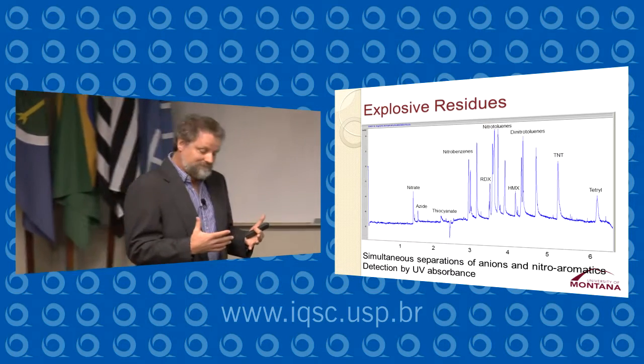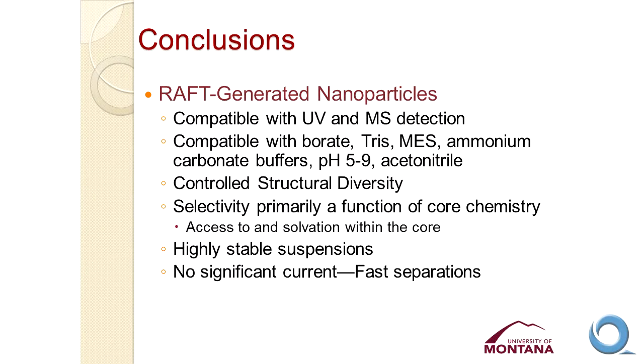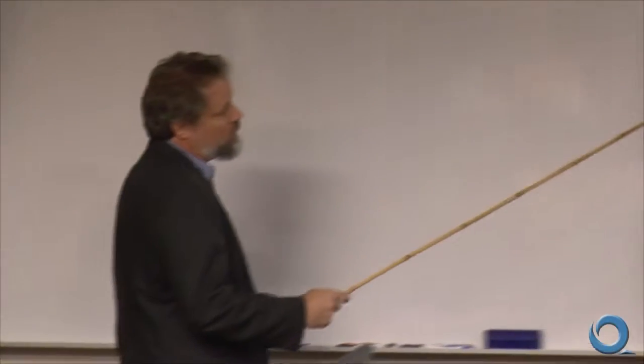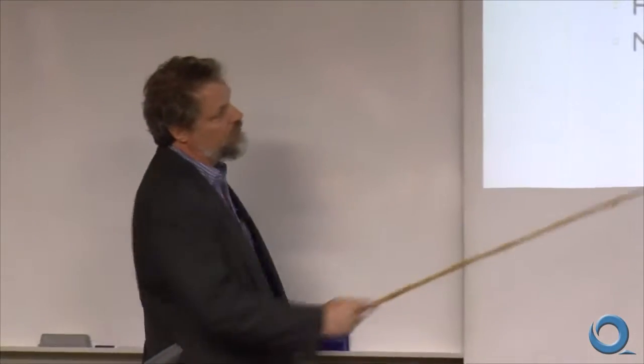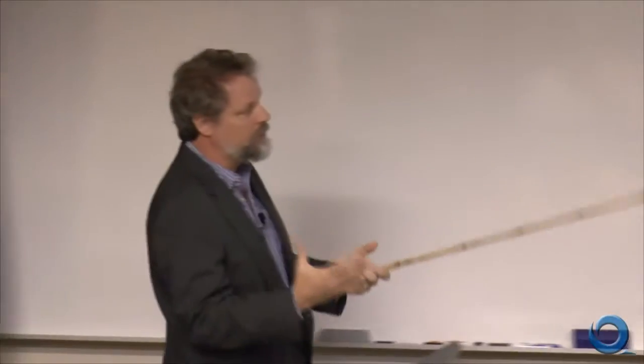Okay, so to finish up, we're pretty excited about these RAFT-generated nanoparticles as pseudostationary phases for electrokinetic chromatography. We've demonstrated that they're compatible with both UV and mass spec detection. We've demonstrated that they're compatible with a lot of different types of buffers, including buffers modified with acetonitrile. We have very strict control over the structure and chemistry of these nanoparticles, and that allows us to alter the selectivity as we like. And we found, up until now at least, that the primary selectivity difference is a function of the core chemistry and not so much the chemistry of the ionic shell.